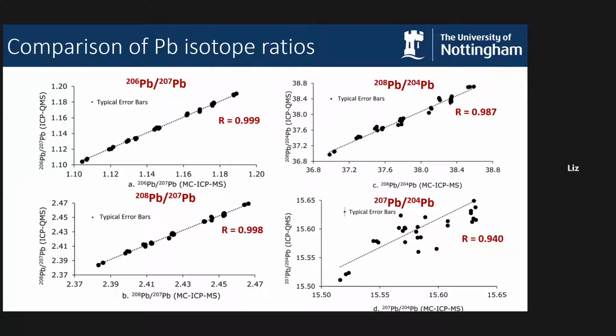The graph at the right at the top there shows the lead 208-204 ratios. That was also fairly good, but a bit weaker than the other ratios I've just mentioned. But it's perhaps understandable why that ratio should not have quite such a good correlation. There's a greater dependence on mass bias because there's a 4 mass unit difference between lead 204 and lead 208. We've got the very low isotopic abundance of lead 204 at just 1.4%. So that gives a lower signal and poorer counting statistics.